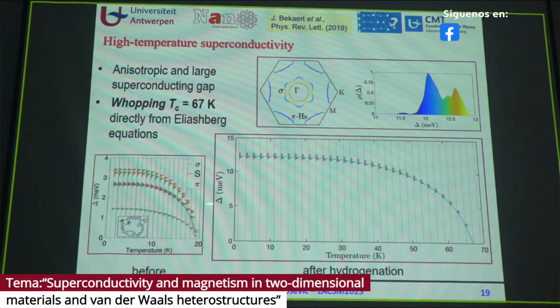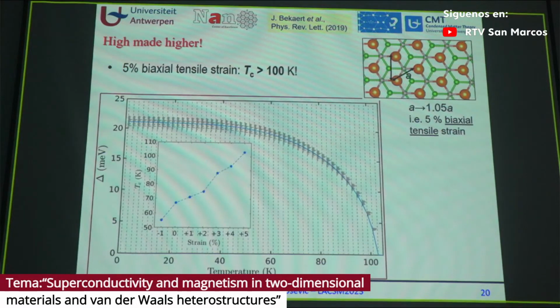So this is without strain. This is just before was 20 Kelvin. With hydrogenation, I go to 67 Kelvin just by adding hydrogen. And if then I strain it, I can exceed 100 Kelvin. This is how the Tc depends on strain in this material.